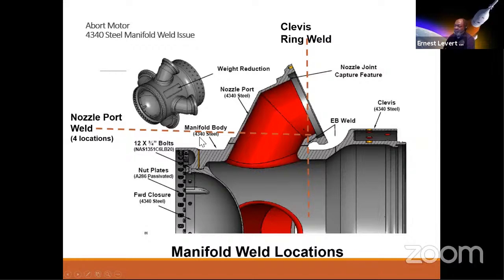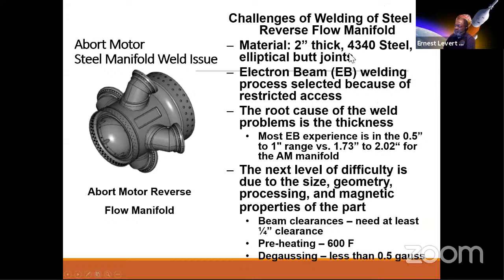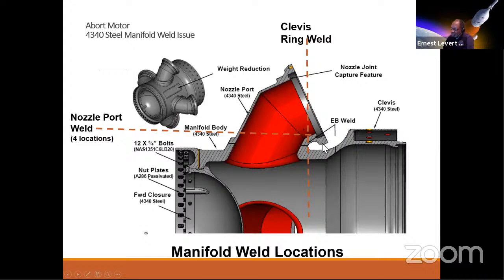And so why was this an issue? The problem we have with this material is, one, you had an EB joint that's 2 inches thick. And more importantly, it's 2 inches thick, 4340 steel. And once again, it was elliptical. So you had major issues with the thickness varying throughout the thickness range. But EB was selected because of the restricted area. The problem that we had was it ranged from a 1/2 inch to 1 inch range to 1.7 inches to 2 inches on the OD. Another problem you had was a very small clearance of a 1/4 of an inch. Let me show you back here again. Trying to get this beam through this 1/4 inch material right here.